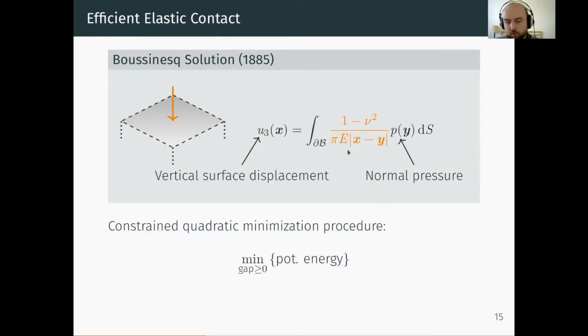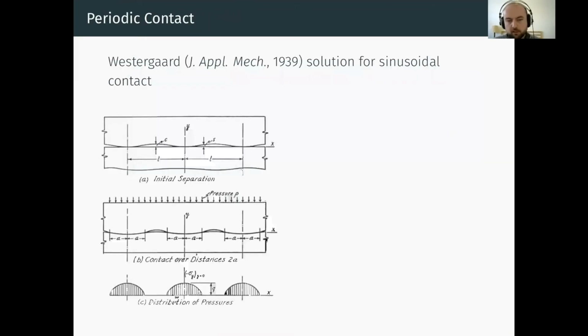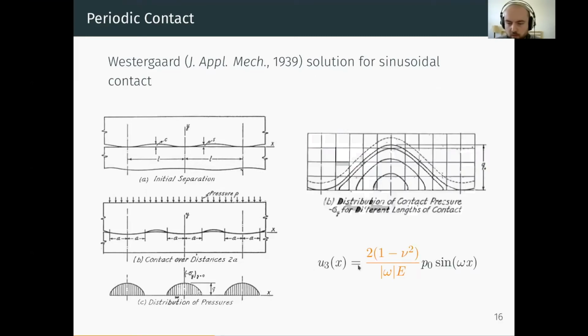Now, the main computational burden of this kind of method is to compute this convolution integral efficiently. And one of the best ways to do that is to go to the Fourier domain to be able to compute it. Historically, that's what people have done. And what they've done is to use a contact solution from the early 1940s, which is the solution of a sinusoidal rigid surface on top of an elastic half space. And so the contact solution is very interesting because as you push the contact until you have no surface separation, you have a correspondence between your displacement and the sinusoidal contact pressures. So you have a proportionality between the two.